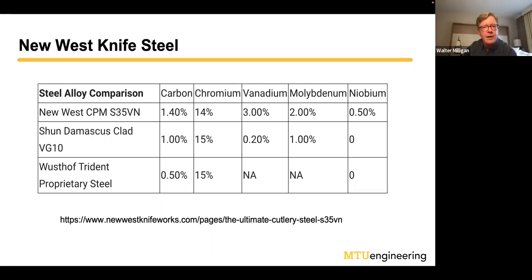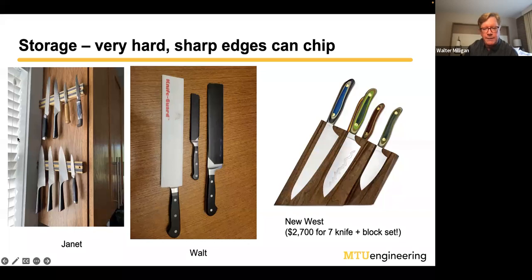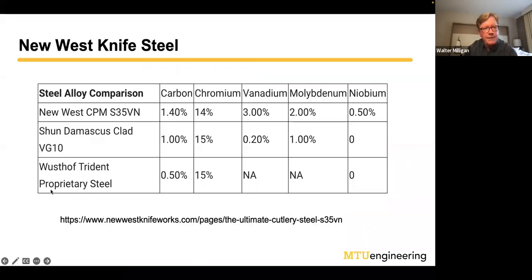It turns out that 2% molybdenum helps a bit with the toughness, for reasons that I don't have time to get into. Shun is a very expensive Japanese knife. They make a lot of Santoku knives. And you can see similar, they've got a very high carbon, about the same chrome, but they don't have as much of these hardening phases over here, so it's not going to be quite as hard. And then, of course, a very common knife, if you are in the kitchen area, is Wusthof, which is made in Germany. I have a set of Wusthof knives that I'll talk about in a minute. Much less carbon and none of this other stuff. And so this is not going to be nearly as hard as that one.